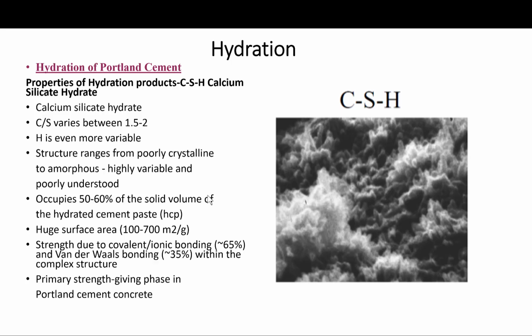The Feldman-Sereda model visualizes the calcium silicate hydrate structure as being composed of an irregular, kinky array of layers, which are randomly arranged to create interlayer spaces of different shapes and sizes, between 5 to 25 angstroms.